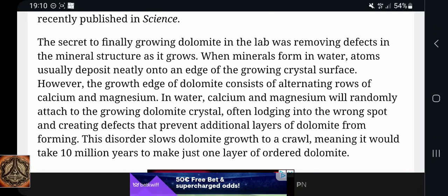The secret to finally growing dolomite in the lab was removing defects in the mineral structure as it grows. If minerals form in water, atoms usually deposit neatly onto the edge of the growing crystal surface. Now one might ask, how does the water know where the surface is? Anyway, the growth edge of dolomite consists of alternating rows of calcium and magnesium.